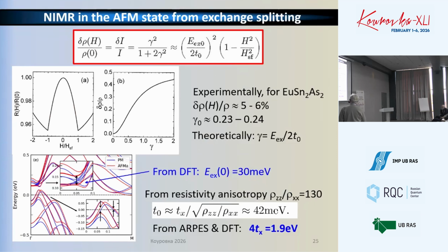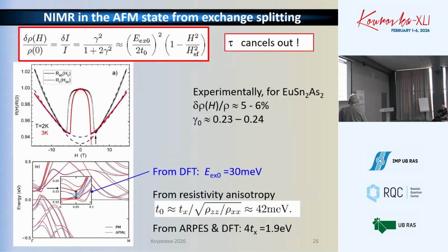So we observe about 6% magnitude of the magnetic resistance in europium tin arsenide. For some other materials, it can be a little bit bigger or smaller, depending on this ratio for particular materials. On top of this parabolic magnetic resistance, of course, you can add the classical omega_c tau squared dependence, which is just additive on top of the negative magnetic resistance I was talking about.